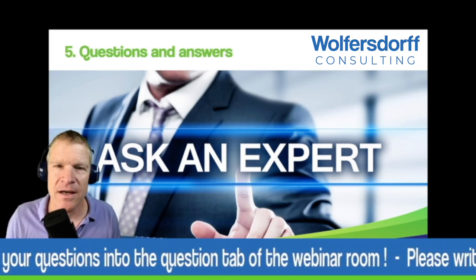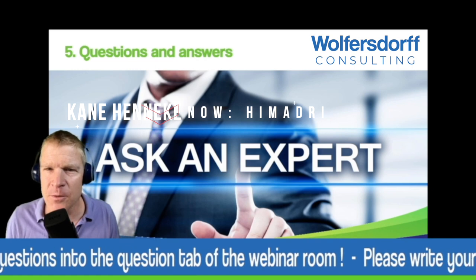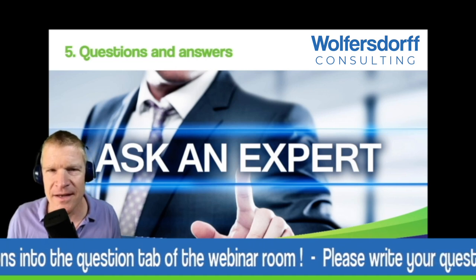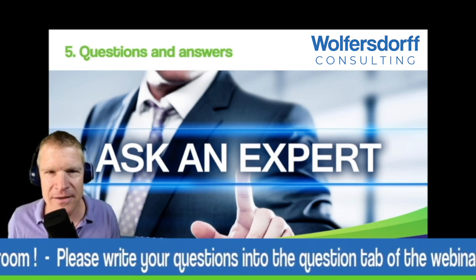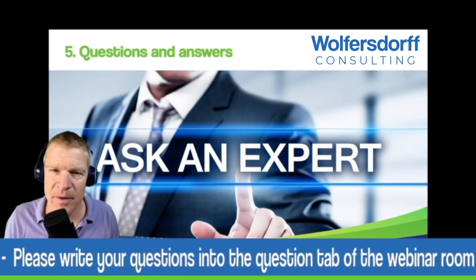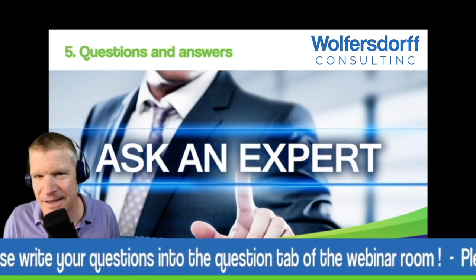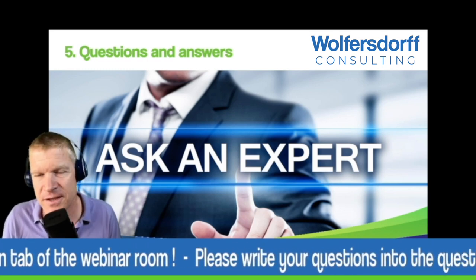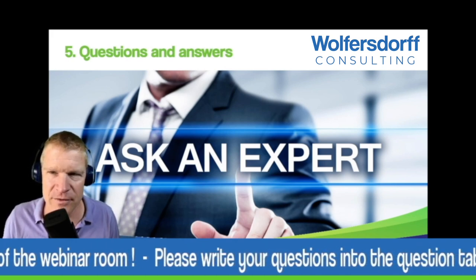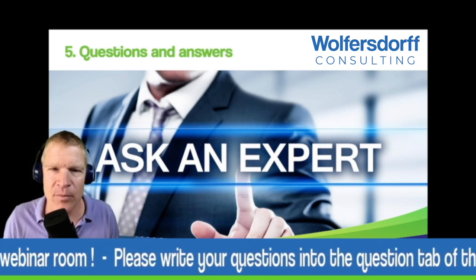Kane from Orion Engineered Carbons is asking, with RCB, does anyone notice having to change screen packs more often? I would say that the problem is that not every RCB is created similar. It depends on the feedstock, it depends on the milling, it depends on the refining. So if we don't mill to underneath 10 microns, and we screen with a screen over the milling size, we will have a pressure buildup, and then we have to change the screens more often. So fine milling is important.